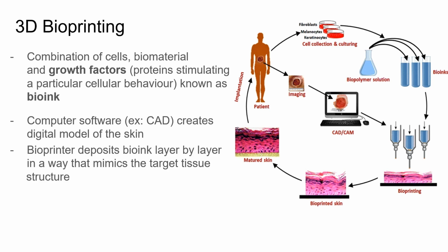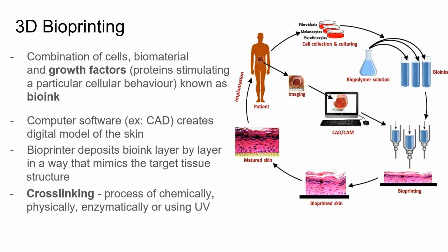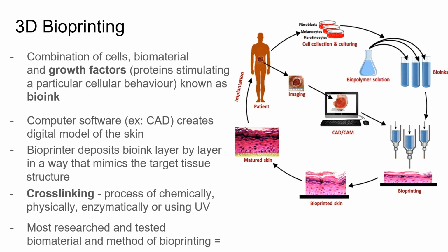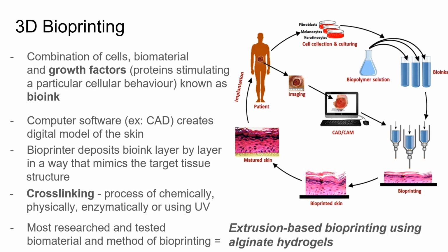The bioprinter deposits bioink filaments layer by layer following the skin image. The graft is then cured and reinforced through cross-linking. Many methods and materials of bioprinting exist, with the most research being extrusion-based bioprinting using alginate hydrogels.